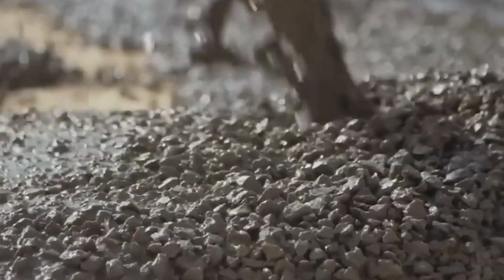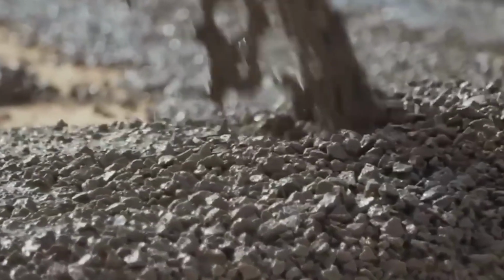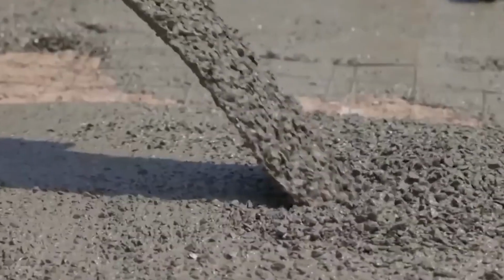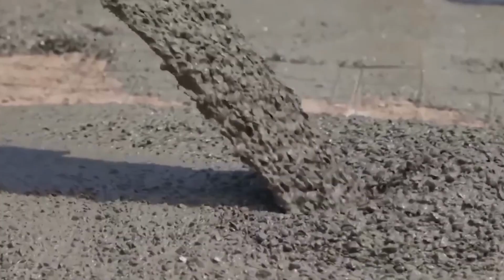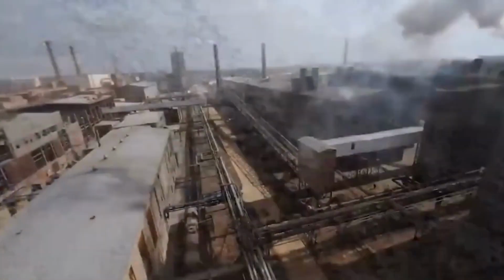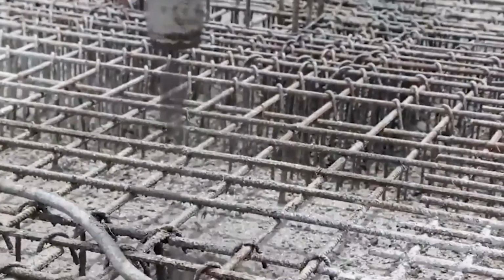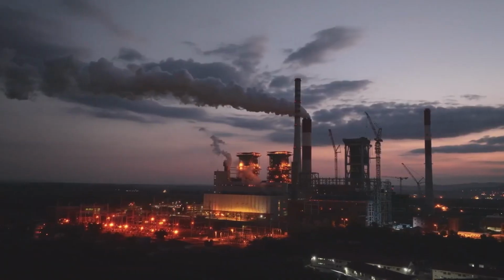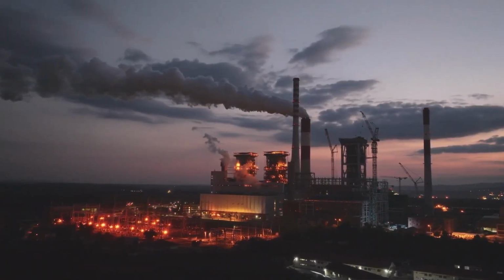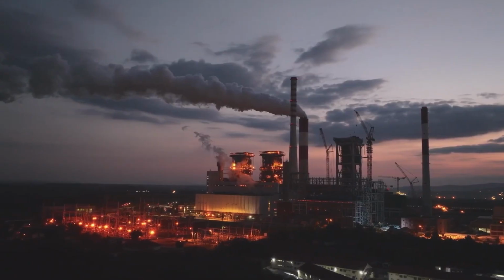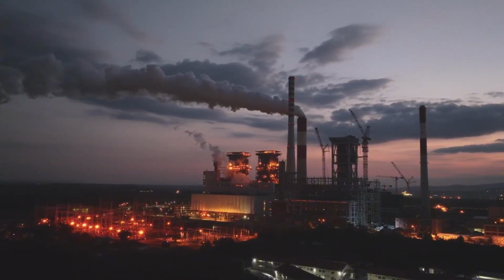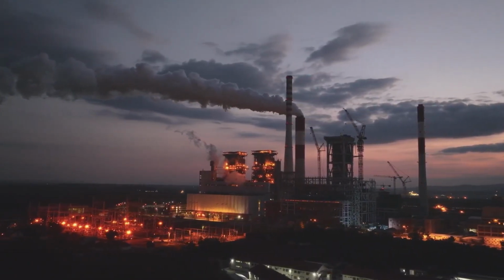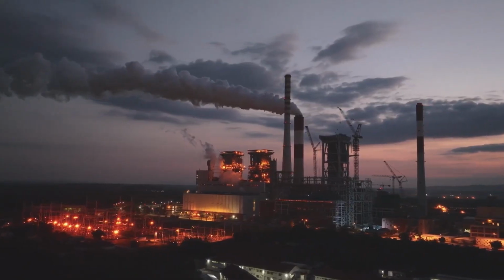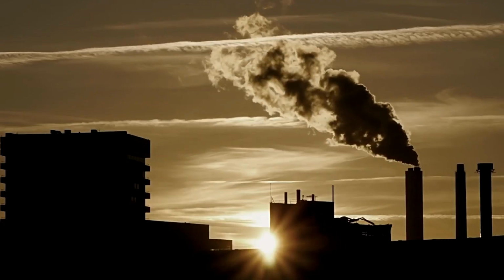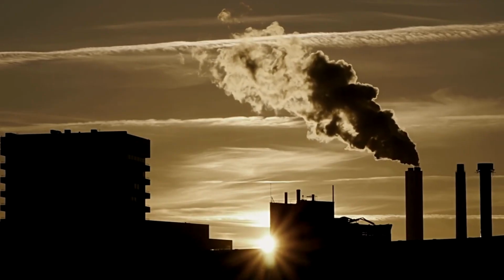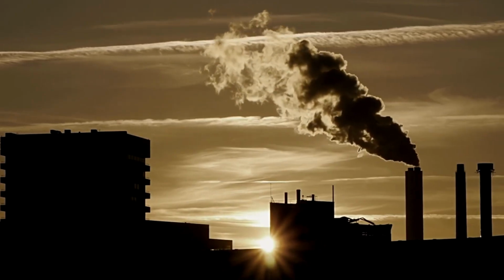The instinct for years was to chase purer, more consistent raw material, essentially trying to make industrial waste behave more like refined cement. That instinct was backward. The actual fix researchers eventually landed on was the opposite. Instead of controlling the raw material, control the activator ratio and the cure conditions precisely enough to absorb the raw material's natural variation. Standardize the process around the inconsistency, rather than trying to engineer the inconsistency away. It sounds like it should not work.